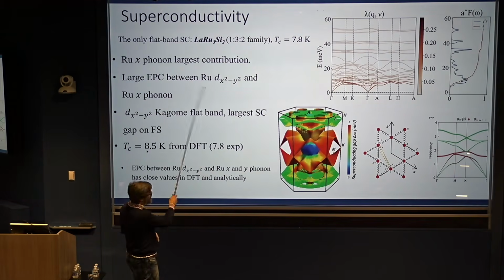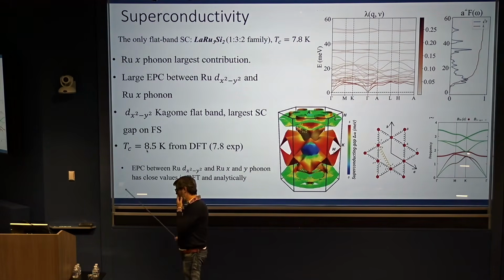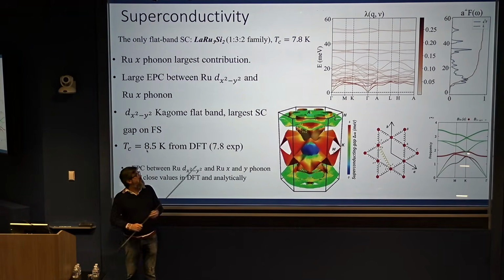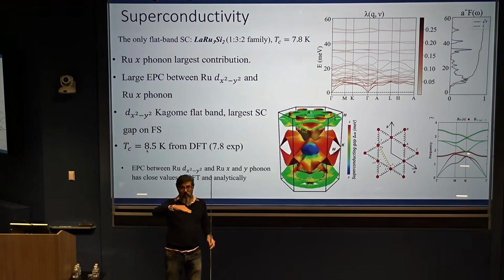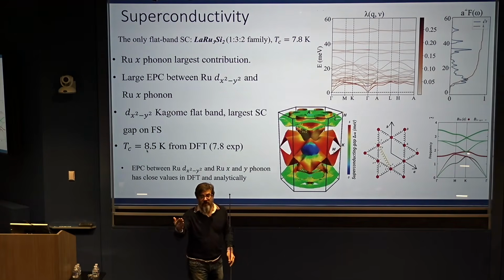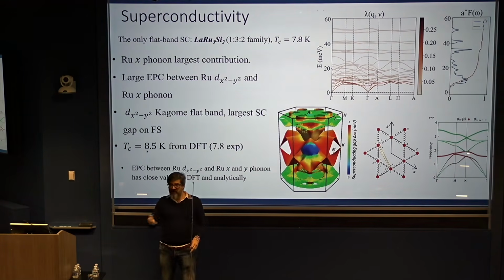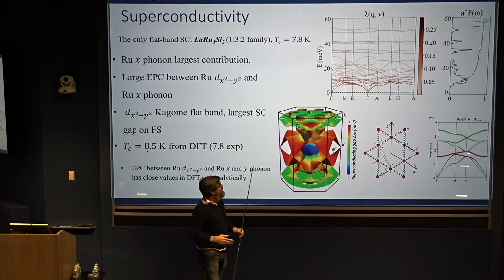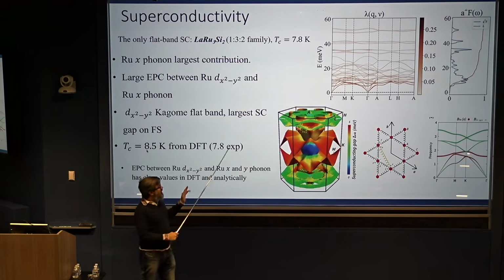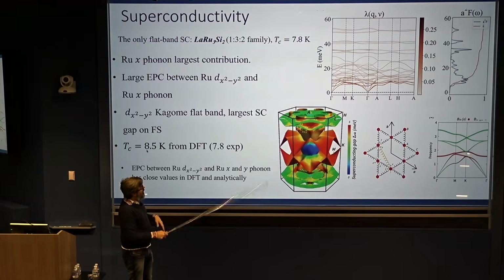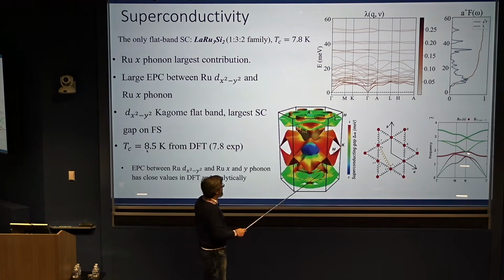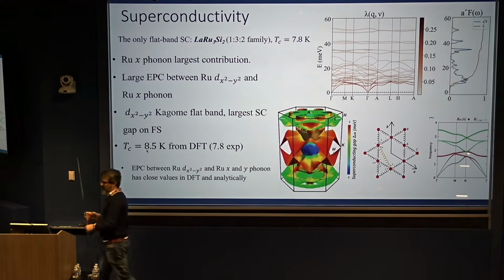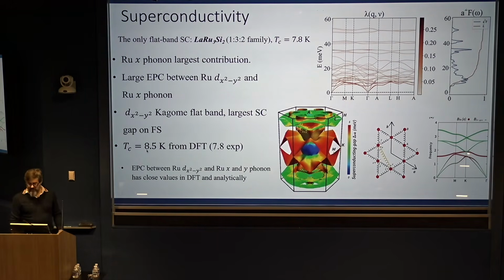This is one example. It was the only example until 2 years ago, or 1 year ago. Now there's a couple more examples. But this is a Kagome where the flat band is almost fully occupied. If it's almost fully occupied, the ferromagnetic or antiferromagnetic tendency is very weak, and you do get superconductivity. We can understand this superconductivity, done in work by Ian Junze and Haoyu and other people, basically as electron-phonon coupled. We get a very good value for TC as electron-phonon coupled.